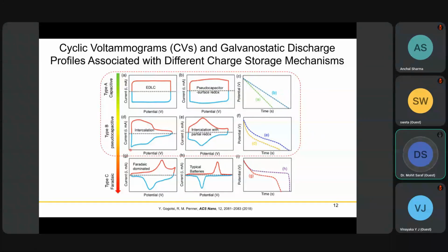But in the case of pseudocapacitors, you will see an impression of intercalation, where there are no evident redox peaks, which can happen because of intercalation pseudocapacitance. At the same time, you can have intercalation of ions with redox reactions - partial charge transfer happens, such as in the case of MXenes in acidic electrolytes. In this case there is no plateau, but since this is potential dependent capacitance, at every different potential the capacitance is different.